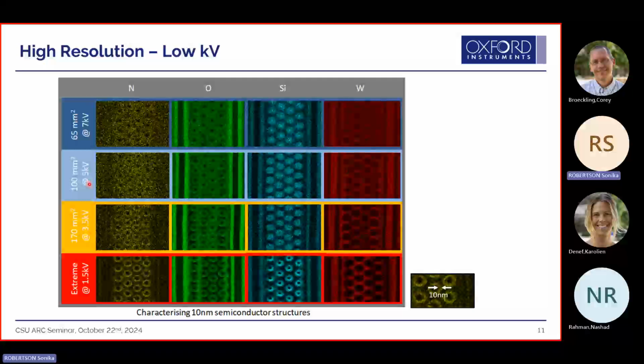And definitely not silly. Some of the things when I learned, I thought, no, you're joking. I've done EDS, but we've come that far, the technology in general. Some of the data I showed you, the surface level, single layer graphene sheet, that's more of, believe it or not, XPS. XPS Auger kind of equipment can be very expensive. So it's not to replace that technique, but being able to still extract more surface level information from the same samples when you already have the tool.